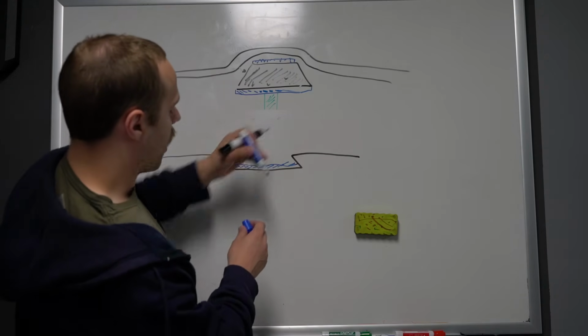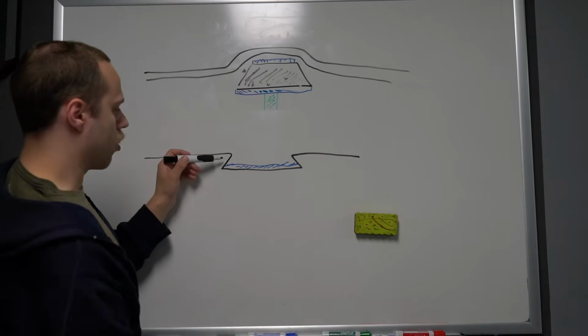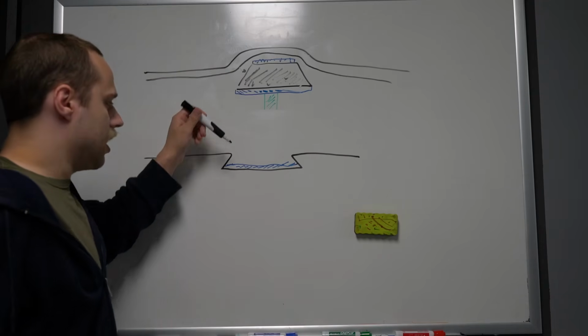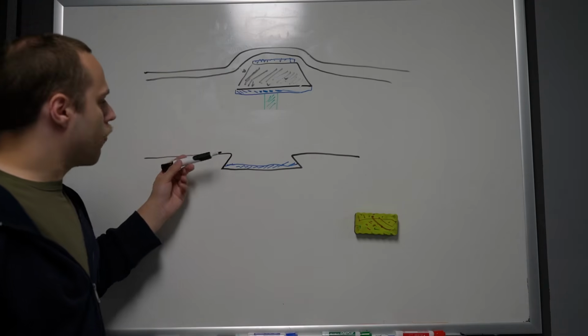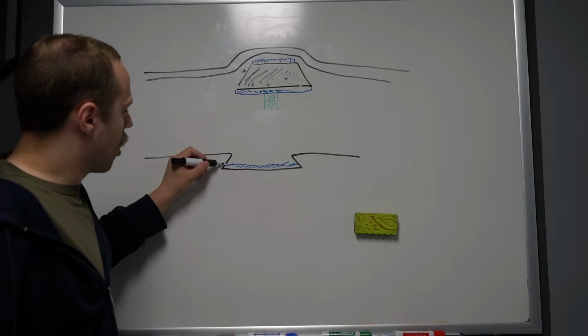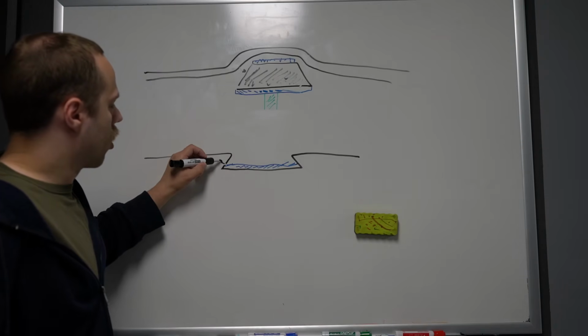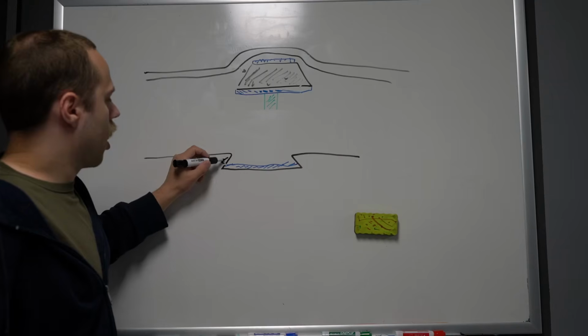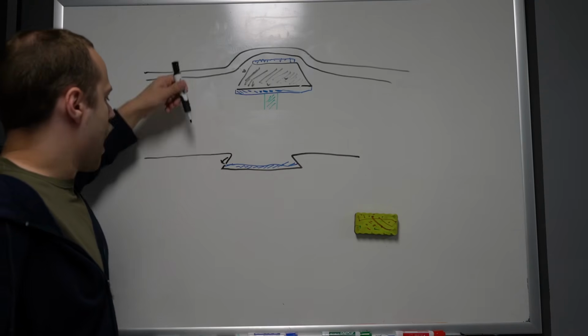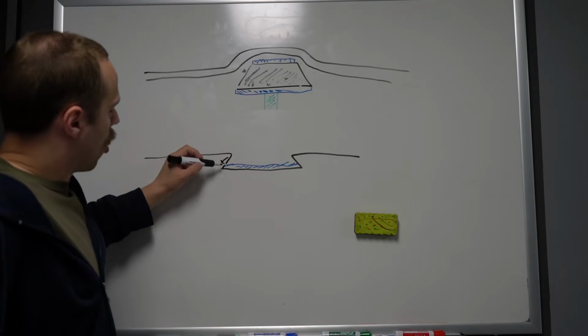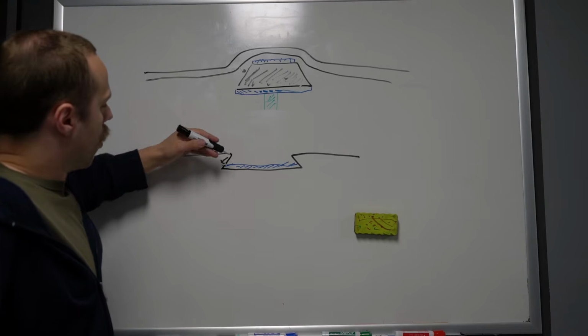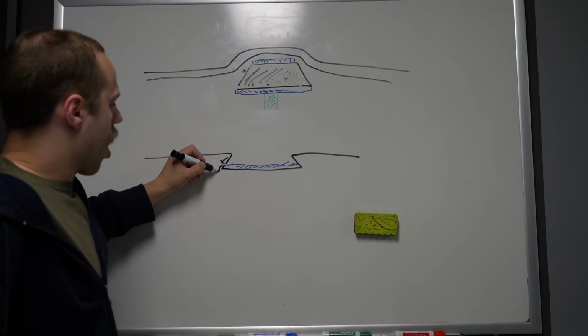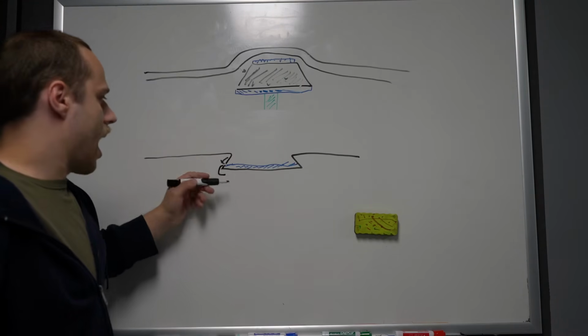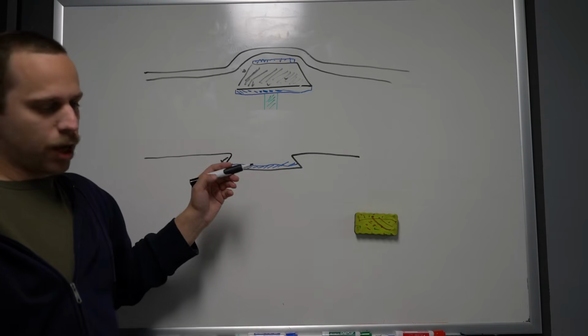And so that's going to provide a barrier against further etching in the downward direction, but the HF etch is isotropic, and so it is going to slowly start eating outwards towards the side. It's going to eat away this undercut, and at the same time we're also etching it from the top. So eventually we are going to remove most of the glass. We're going to get down to this area. We are going to start undercutting the titanium nitride, and at that point it will eventually float away and be removed.